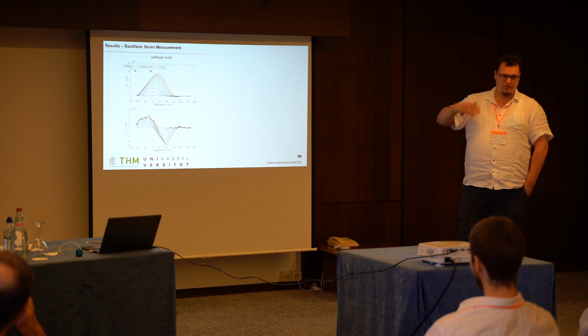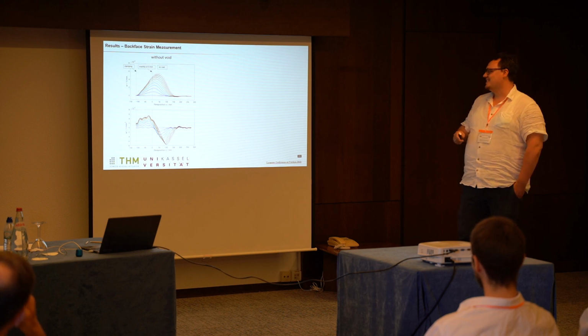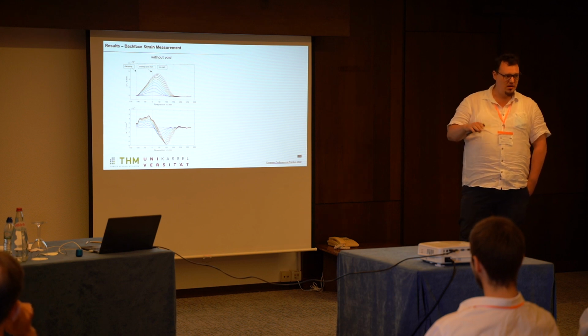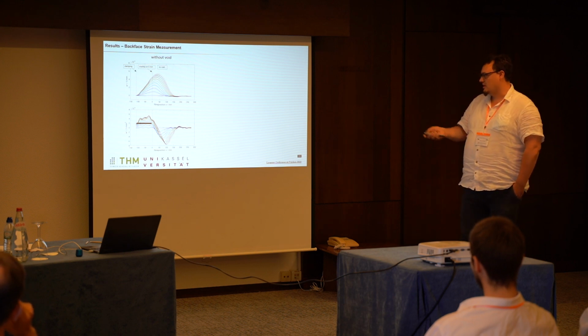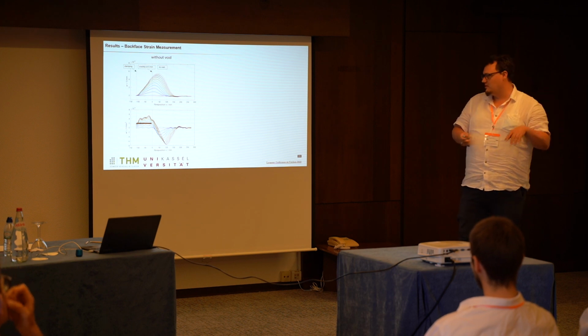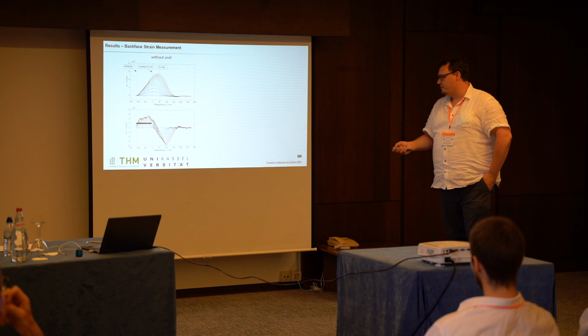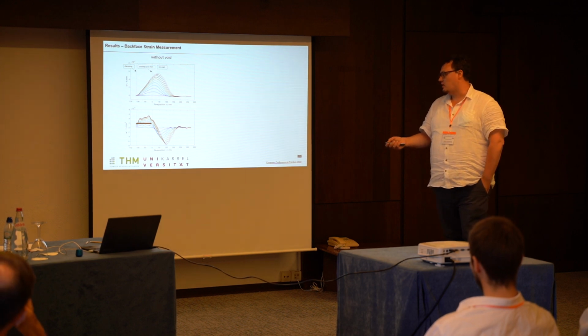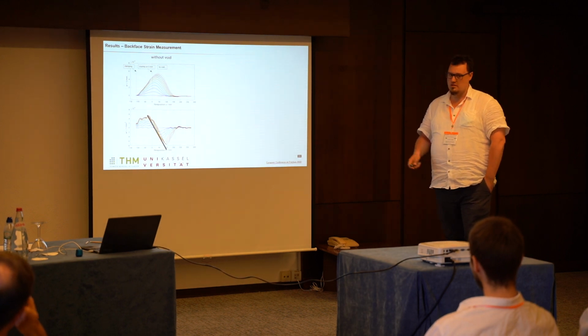And then we differentiate this once, and now we're searching for a constant value in these curves. There is something in the front, but that's the lever arms of our specimen. That's no void. And in the area of the adhesive behind our crack tip, there's only a decrease and an increase and no constant value.